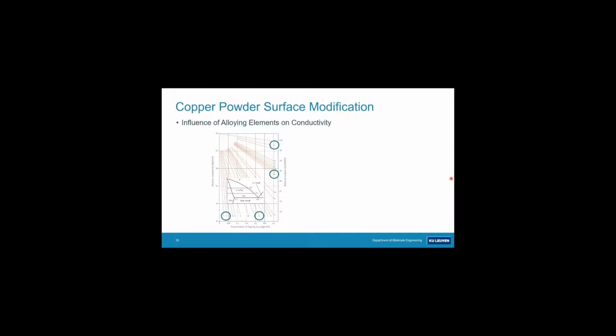Another thing to bear in mind, thinking about the idea of surface modification of powders: anything you introduce into your powder will have an effect on the conductivity. And especially the solid solution forming elements such as nickel, so this is for elements all in solid solution, nickel has a significant effect, and you see other elements such as phosphorus, which is often there as an impurity, or titanium or chromium in solid solution. They have very limited solubility, but they do have a very significant effect on the conductivity. Of course, at even higher nickel content, since nickel and copper are mutually soluble over the whole solubility range, there is a very drastic decrease in conductivity from the moment you exceed a few percentages of nickel.